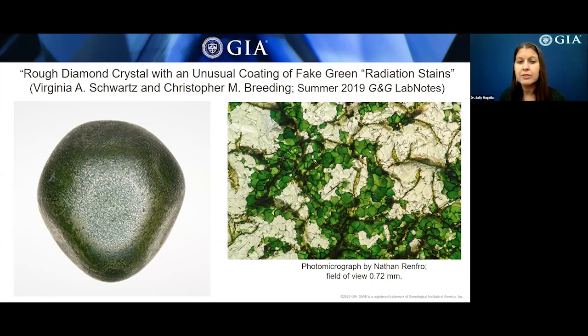The green platy crystals, they're about 40 microns in size, were attached to the diamond surface. Authors were able to easily flake off using tweezers or a pointer probe, but under most normal gem testing situations, like holding it in tweezers or rubbing with the stone cloth, those crystals remained adhered to the surface. X-ray fluorescence indicated that it had high concentrations of chromium, and then the Raman analysis identified these green plates as chromium oxide. The Raman positions correlated very well with chromium oxide powder that had been heated to 700 degrees Celsius to produce a crystallized coating and probably to help with the adhesion to the diamond surface.